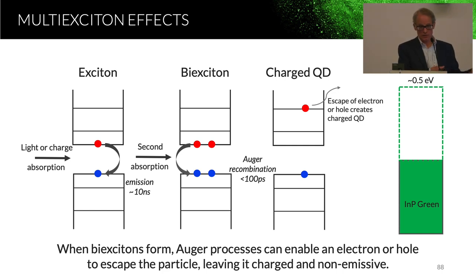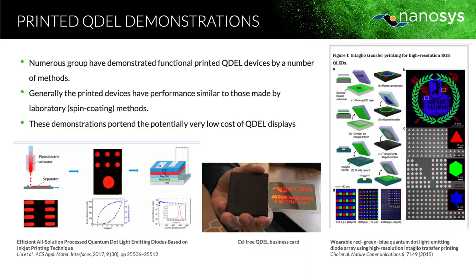The converse thing can happen too. You can also have what's called a hot hole. But either way, you have a very energetic particle that has the potential to escape the dot. And if that happens, now you have just a positive charge where the electron once was. It's a charged particle, and it's not emissive. So this is something that, through these structural studies and structural engineering of the dots, people have been able to figure out ways to minimize.